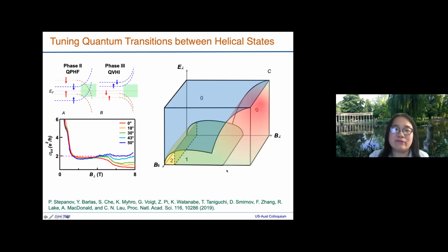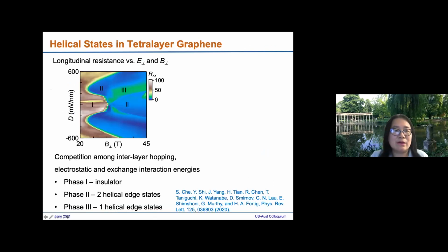Okay, so this is what we have. This is the summarizing phase diagram. We are plotting it as a function of out-of-plane electric field, perpendicular magnetic field, and parallel magnetic field. The numbers here indicate the number of edge states. We can have 0 edge states, 1 edge state, 2 edge states, and when you add in-plane magnetic field, you can continuously change it from 0 to 1 edge state. This is what we find in trilayer graphene. We recently also have a work on tetralayer graphene, but for the interest of time, I'm not going to go into it.